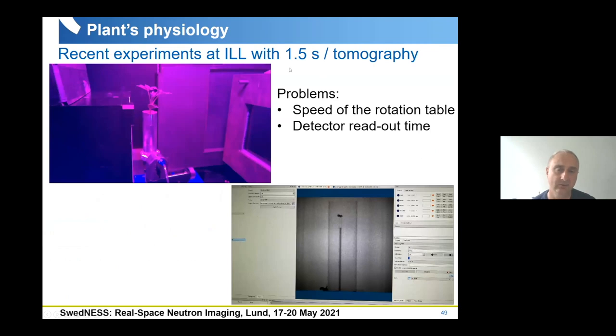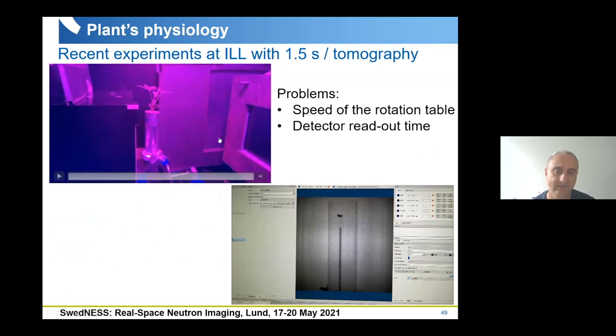Last year, we were able to perform 1.5 second tomography at ILL with their high flux. And this is how this looks in reality. So this is the speed of this, let's say 1.5 seconds over 180 degrees. This is just for your feeling of how the speed is, and that we don't really have a problem with the centrifugal forces for the water. So this is quite moderate speed, and then we can investigate the water uptake in the plant with 3D.